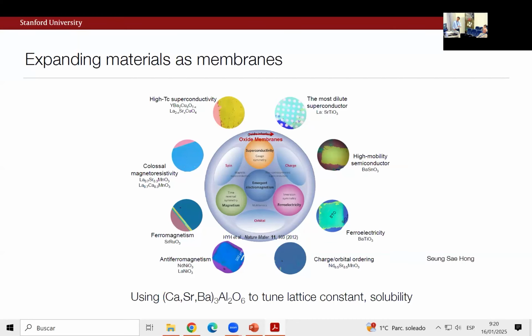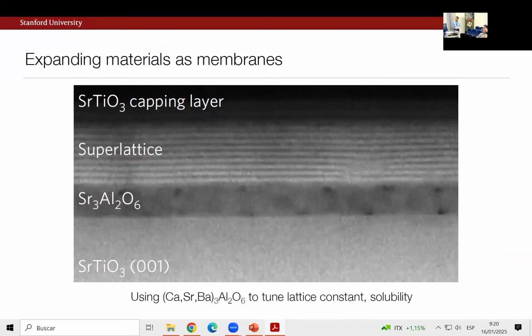And as we grow these different kinds of systems with different constraints and lattice constants, let me just summarize a lot of work and say that we've been using these different versions, calcium, strontium, and barium, to tune solubility and the lattice constants. And to give you a very simple visual graphic of the types of things that we're finding, this was actually just a blow up from that earlier cross-sectional image I showed you 2 slides ago. So this is the manganite titanate superlattice. What I want to draw your attention to is this buffer layer. You see these dark circles here, right? So these are actually dislocation cores.